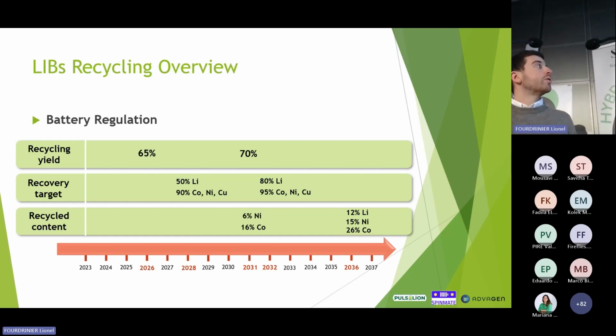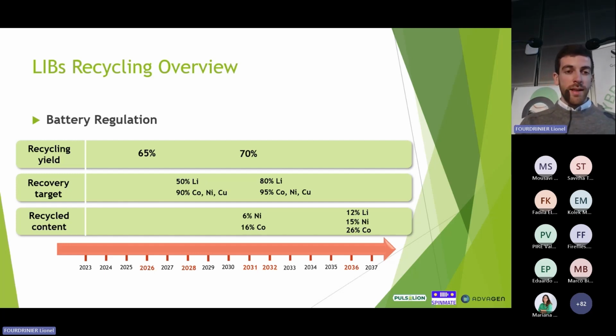And finally, there is also one target related to the content of recycled material in the new batteries. So by 2031, the target is to have at least 6% of recycled nickel in the new batteries and 16% of recycled cobalt. And then by 2036, the lithium is also included. So the target is to have at least 12% of recycled lithium in the new batteries, 15% nickel, and 26% cobalt. But as they mentioned, we will have this discussion panel later about the battery regulation, so we'll have time to learn a bit more about this.